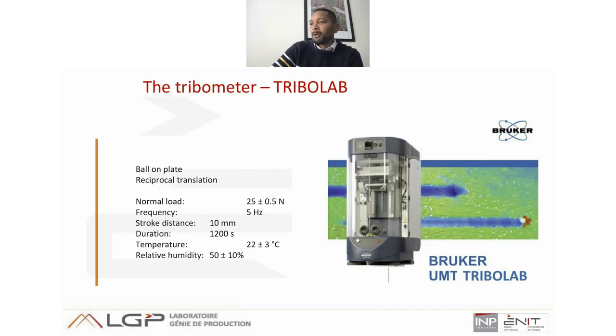We use the Tribolab for our experiments. This is a tribometer from Bruker. The contact is a ball on plate in reciprocal translation. The normal load is 25 Newton, frequency 5 Hertz. The stroke distance is 10 millimeter, and we present tests at 1,200 seconds, but we can run more or less to study the kinetics of wear. We work at 22 degrees temperature, and the relative humidity can be controlled at 50%.